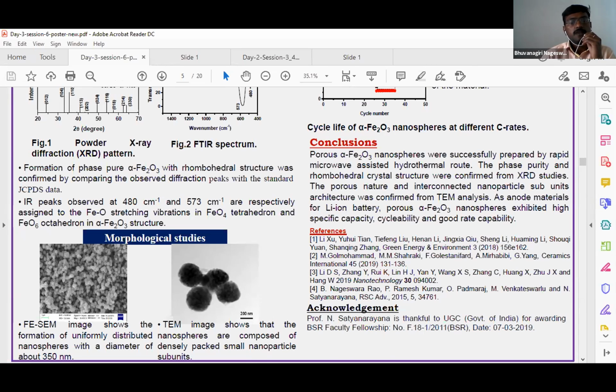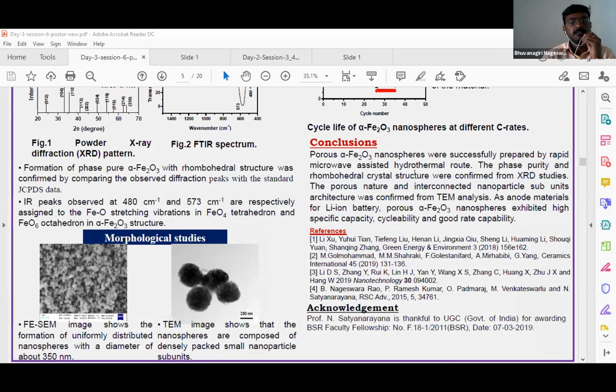Later we examined the size and shape of the prepared material using SEM and TEM. In the FESEM images, it clearly shows the formation of uniformly distributed nanospheres, which have an average diameter of 350 nanometers. If we use conventional methods and apply high temperature, we can have an agglomeration problem. But here in the microwave synthesis, at low temperature and without post heat treatment, we can get uniformly distributed nanoparticles.